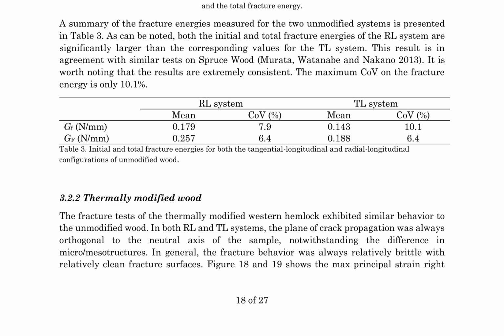Fracture tests on thermally modified Western hemlock wood exhibited similar behavior to unmodified wood, with both RL and TL systems showing brittle fracture behavior and clean fracture surfaces. The plane of crack propagation was orthogonal to the neutral axis of the sample, regardless of micro-mesostructural differences. The results indicate that the thermal modification process does not significantly alter the fracture behavior of the wood, as the RL and TL systems exhibit similar behavior to their unmodified counterparts.